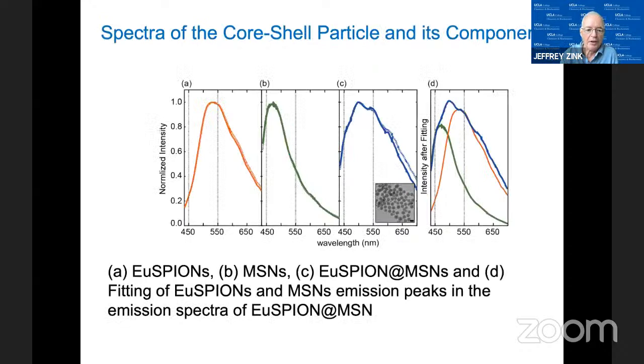So we measured that. We doped the magnetic particles with europium-3, so we were able to get a red emission from that. The mesoporous particles themselves have a blue emission from defect centers, dangling Si bonds in the silica matrix. And so we had two different bands. We could look at the core and we could look at the shell. They overlap a bit, but we can choose regions of the spectrum where we see primarily core or primarily shell, and we could measure if there's motion.